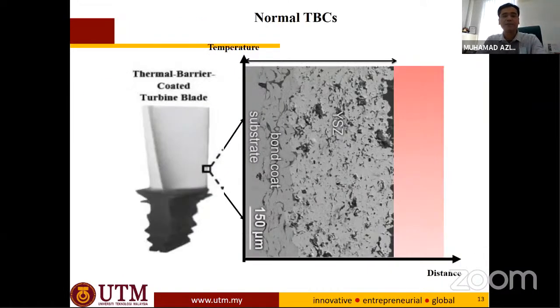Right, so if you look in detail at one single turbine blade and observe under a microscope, this is basically the geometry of the cross-sectional view. This is the substrate, as I said just now, maybe made from nickel superalloy, and they have another layer, the bond coat, here. Why is the bond coat here? Because you want to deposit the ceramic. You see the different colors: the ceramic is bright, then there is the metallic bond coat, and then the substrate. The bond coat basically reduces the mismatch in coefficient of thermal expansion between the ceramic and the substrate. Because without this bond coat, the difference in coefficient of thermal expansion between the coating and the substrate would cause delamination of the coating.